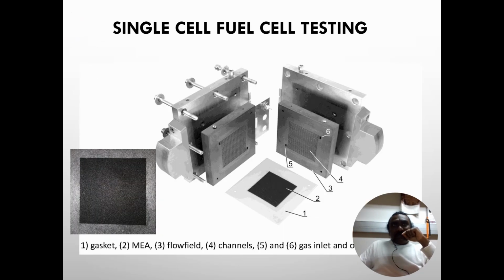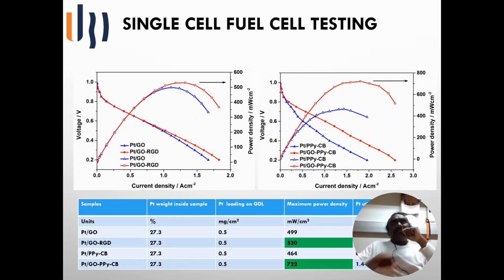This is the typical setup for single cell fuel cell testing, as you can see in the inset. This is the carbon fiber, carbon paper, and we have deposited graphene ink, graphene and platinum nanoparticles with the Nafion ink on the carbon paper. We have used a Nafion membrane in between as a proton exchange membrane, and we have tested single cell fuel cells.